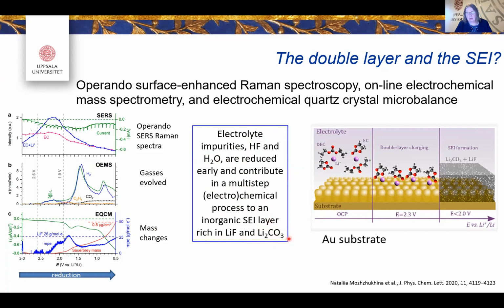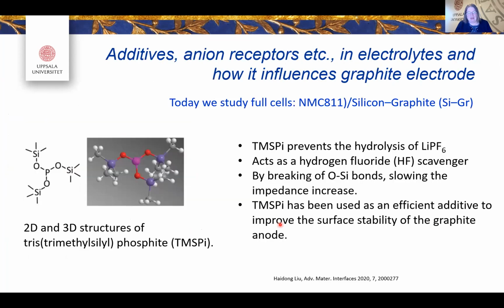And if you remember what I said earlier, that lithium carbonate is not really there, I would say in this case we take that as a name for all the carbonaceous species you have in this formation. As a photoelectron spectroscopy person, it was good to see that you have gases, yes, these will be pumped off in an ultra-high vacuum system, but it seems to not matter so much because it has sort of left the SEI as it is. So it means that the experiments we are doing in ultra-high vacuum are not that dangerous when it comes to composition.